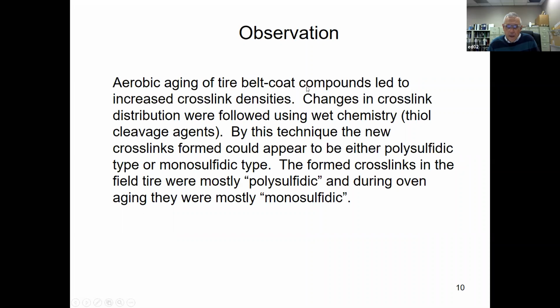So we say the aerobic aging of the belt coat compounds led to increased crosslink densities. Changes in the crosslink distribution were followed by wet chemistry, thiol cleavage agents. By this technique, the new crosslinks formed appeared to be either polysulfidic type or monosulfidic type. The formed crosslinks in the field tire were mostly polysulfidic, and during the oven aging, they were mostly monosulfidic. So we say, you know, they're not really polysulfidic and they're not really monosulfidic, but there's some type of chemical structure that shows up in this test as having a different chemical structure.